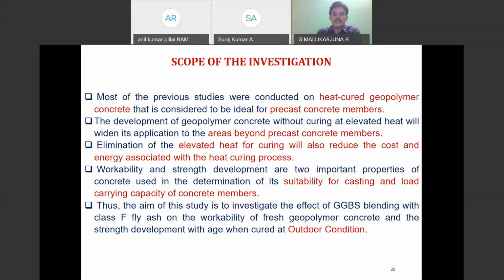But here, with workability and strength development, there are two important factors. One is that we cast the specimens in in situ condition, and one more thing is that there is a limitation: we have to give a certain amount of heat to get the strength if we go with fly ash based geopolymers. My research mainly focused on this mix design methodology, and we produced concrete from 20 to 60 MPa. We replaced 100% cement with fly ash and GGBS in different combinations, and water with the alkaline activator solution of sodium hydroxide and sodium silicate, and we maintained the concentration of the sodium hydroxide at 8 molar.